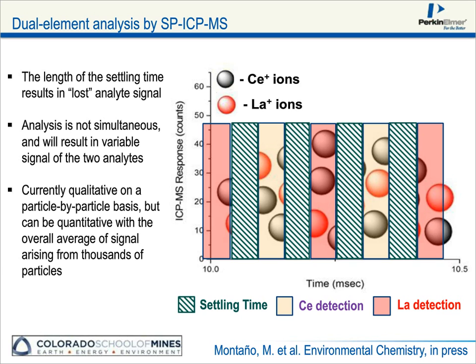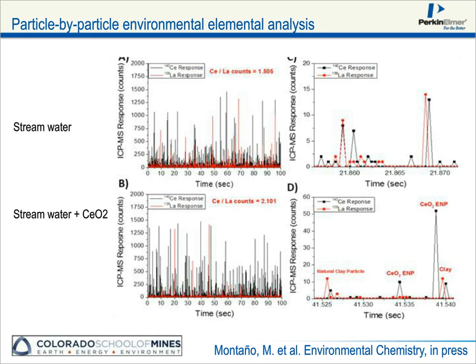But what we found is if we integrate over enough particles, a few thousand, we start to integrate out some of this problem of lost data. So as an example, if you look at a local stream water sample, the raw data is on the left, and you also introduce cerium oxide into that sample.